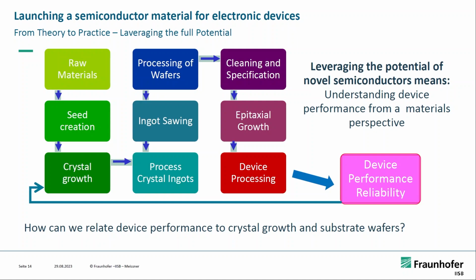So if you're processing the wafers, slicing them and cleaning them and putting them in the box, the people doing epitaxy want to take it out and apply voltage - it should function with no issues, no bumps, whatever, and you must ensure that in the actual process. Cleaning and finishing of the wafers is a big issue, despite everything that comes from the material properties. Then you do the device processing, you have a device, you check the performance and reliability.